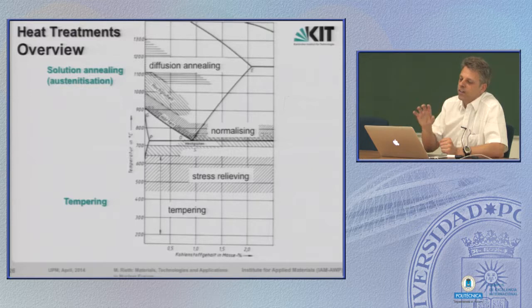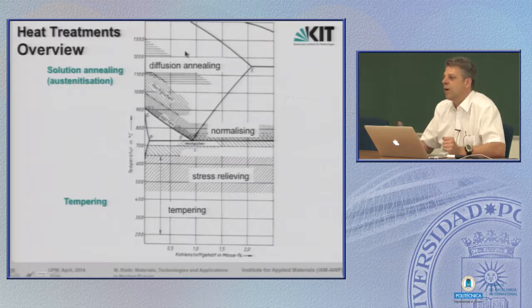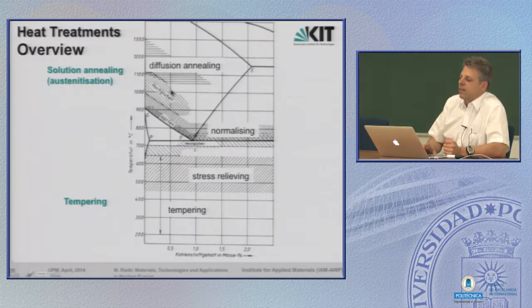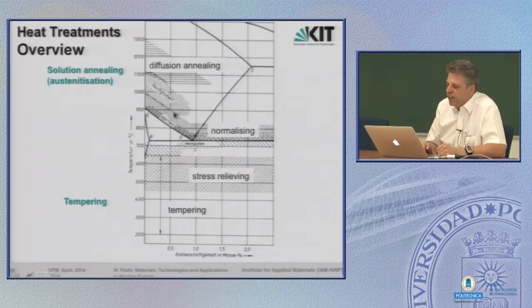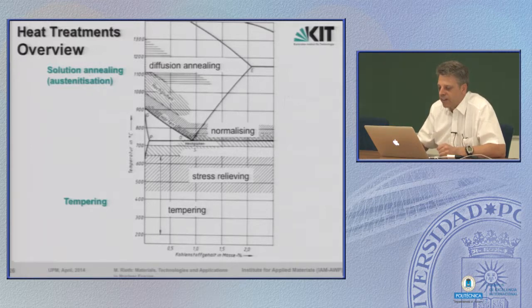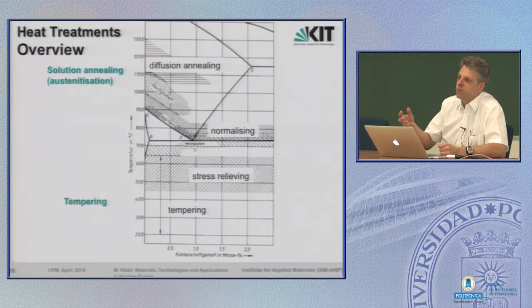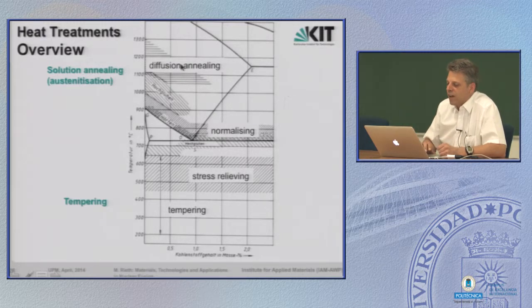This is all the heat treatment which brings you into the austenitic phase and which dissolves all of the carbides and whatever you have in your steel. This is often called diffusion annealing or high temperature annealing, or it's also called hardening, even though nothing is hardened yet. It's the first step to produce a hardened steel, because you produce this austenitic phase, but you have to quench it down rapidly enough to produce this hard martensitic phase. And also frequently it's called normalizing, whatever. So this is the first part of the heat treatment to produce the austenitic phase.